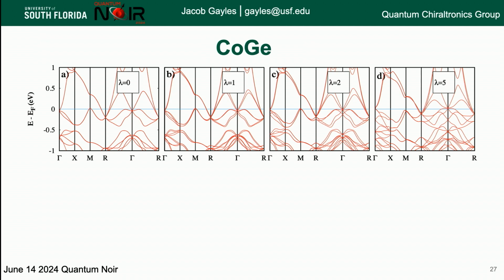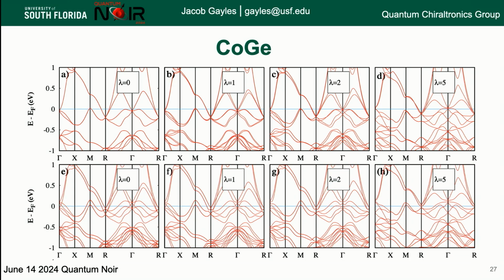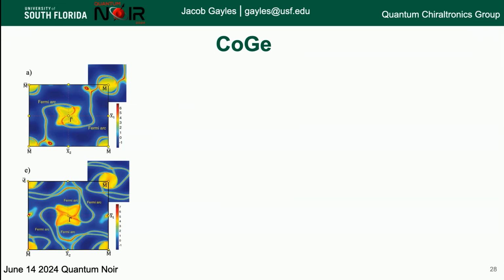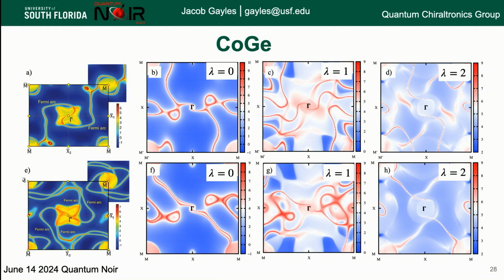Now, the next step is we have to add in magnetism, right? Because we want to have that skyrmion with the Weyl points. And that is also the case here. We keep those Weyl points when we add magnetism. They start to move in momentum space, but we're able to keep those Weyl points throughout. And then here, I'll show you quickly the Fermi arcs with spin-orbit coupling for the different compounds, which stay there.